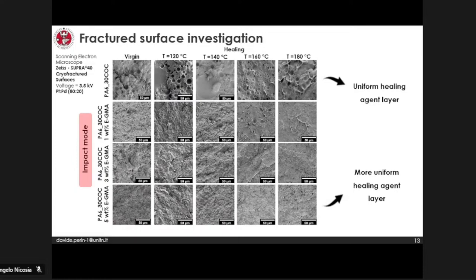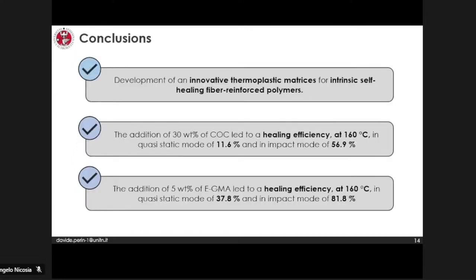So in conclusion, we succeeded in developing this matrix. Without the compatibilizer, we reach poor healing efficiency, but thanks to the introduction of the 5% of compatibilizer, we reach healing efficiency of nearly 38% in quasi-static mode and nearly 82% in impact mode with a healing process of 160 degrees C. But what about the future?